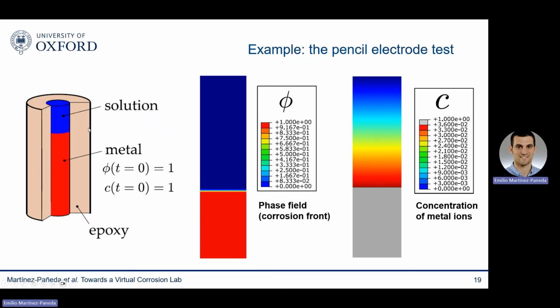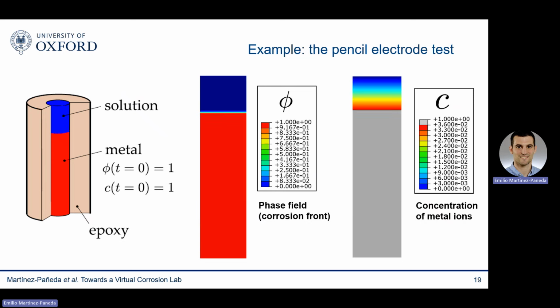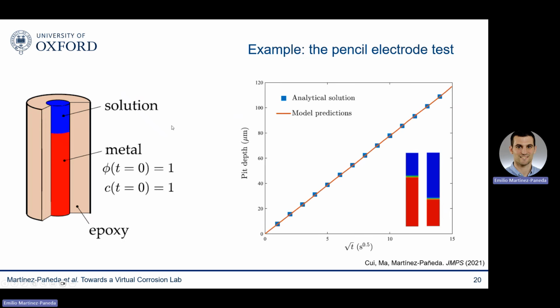You can see here some representative results. On the left, the evolution of the corrosion front, as described by the phase field, and on the right, the evolution of the concentration of metal ions in the electrolyte. And the good thing is that for this 1D problem and conditions of diffusion control corrosion, there's an analytical solution, so we can confirm that the model is giving us the right outputs, as you can see here.